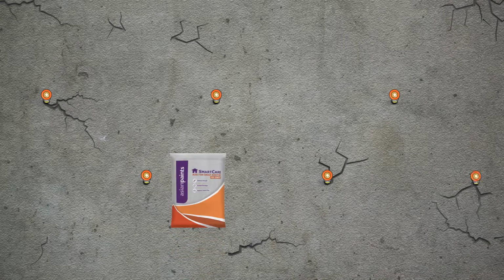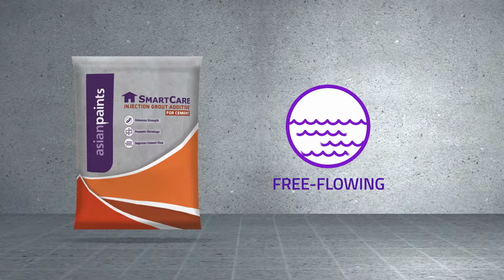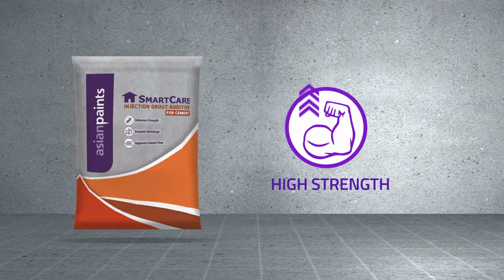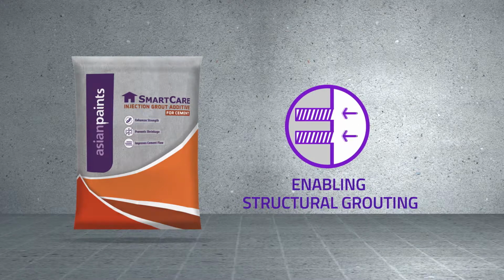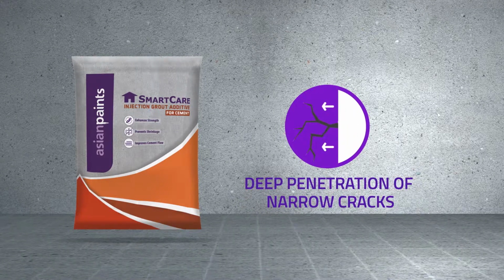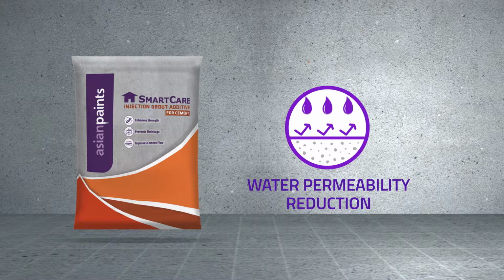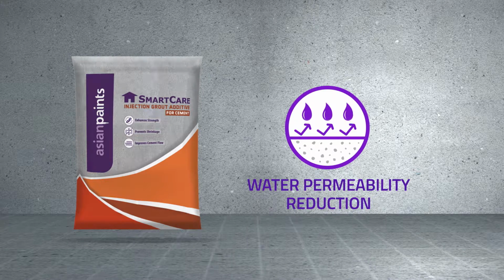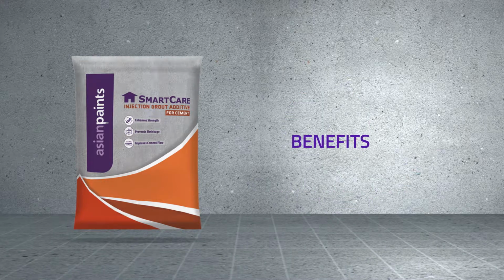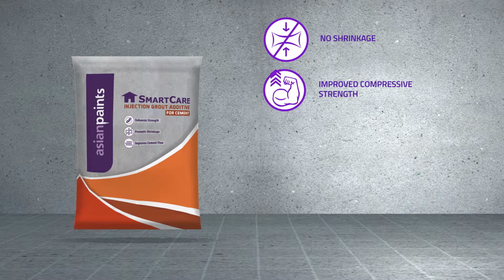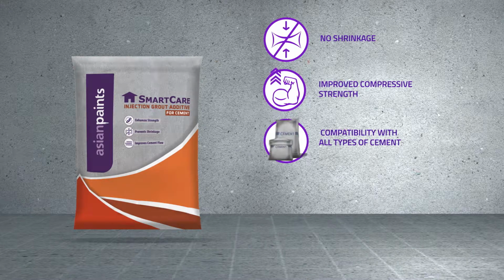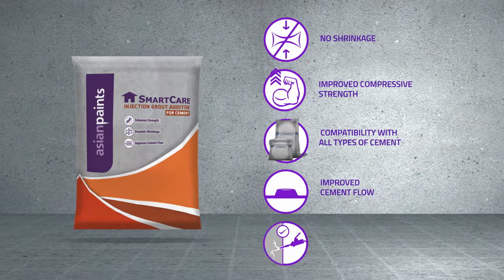Asian Paint SmartCare injection grout additive for cement is a plasticized expanding grout admixture that produces a free-flowing and high-strength grout, enabling structural grouting, deep penetration of narrow cracks, and water permeability reduction. When added to cement, it provides the following benefits: no shrinkage, improved compressive strength, compatibility with all types of cement, improved cement flow, ease of application.